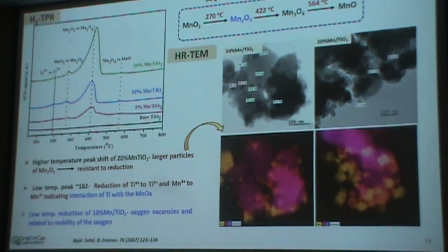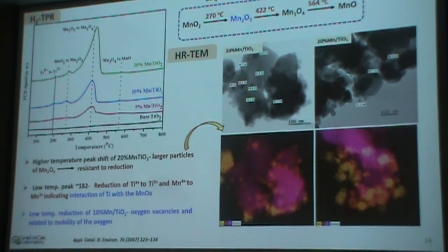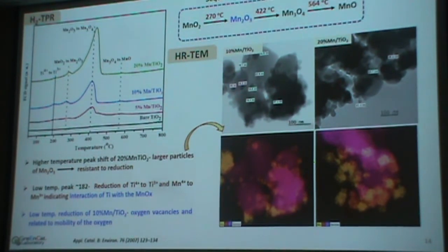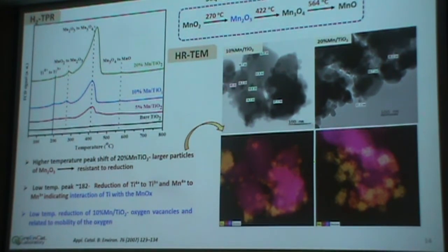And the extent of reduction has also been checked for the same catalyst system. As we know, in the case of manganese oxide catalyst, the reducibility of the oxide support is also important for the activity of the catalyst. TiO2 doesn't show any reduction peak, which means it is quite stable. But as we loaded the Mn, a small reduction peak is observed at lower temperature. That means there is a reduction of Ti4+ to Ti3+ due to interaction between Mn and TiO2.